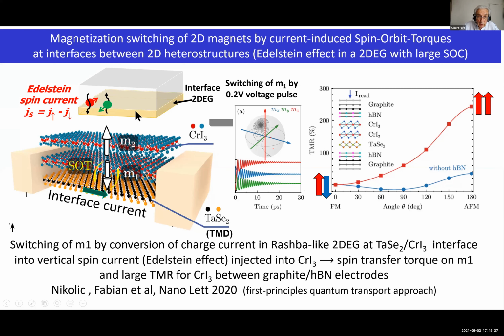In a 2D electron gas at the interface, typically a Rashba electron gas, or another type of 2D electron gas, the Edelstein effect is that when a current is flowing in the 2D electron gas, it polarizes the spin in the gas, and this is the Edelstein polarization. And this polarization of the 2D electron gas can also emit a spin current into the material on the other side of the interface, like the emission by the spin Hall effect. But now the emission is not by the spin Hall effect, but by the Edelstein effect in a two-dimensional electron gas. And so in 2D magnets, it's clear that the spin orbit effect that can be exploited is this interfacial effect, rather than the spin Hall effect, which is typically a 3D mechanism.